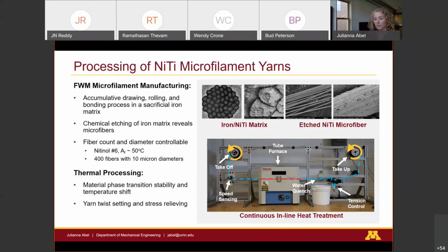So how are we making these? We're getting these bundles of filaments from Fort Wayne Metals. We have gotten filaments between 5 and 10 microns, and bundles between 4 and 1,000 filaments, and they etch away the iron matrix that they draw them in, and then we bring them in and we do some thermal processing within the lab in order to stabilize our transition temperatures and twist set or stress relieve the yarns.